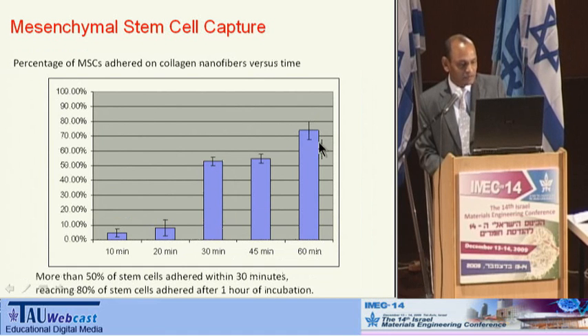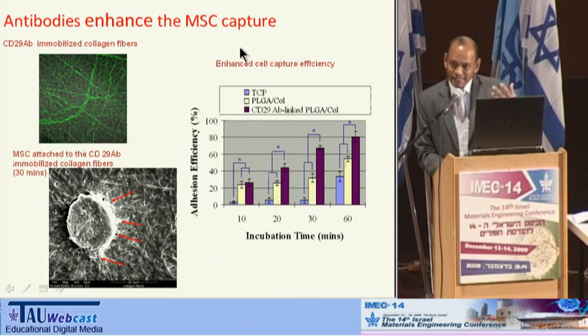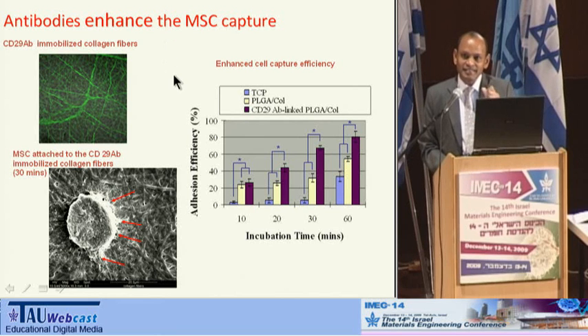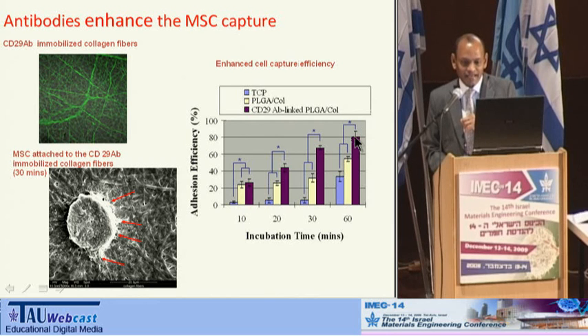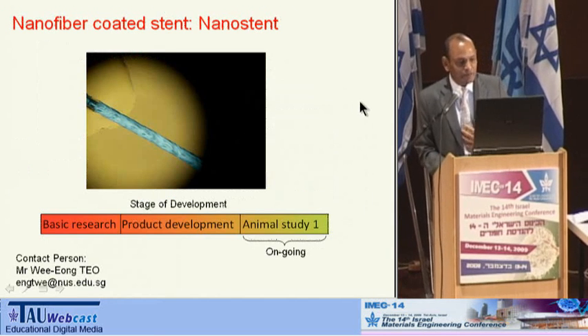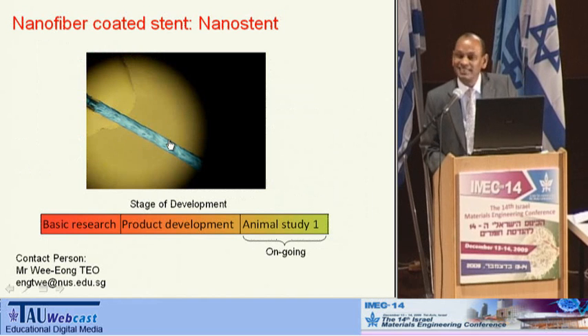And of course, if you further optimize it, you could get much higher levels of retention of the bone marrow cells, almost close to 80%. And then you can further enhance this by optimizing the surface of the collagen nanofibers with certain protein molecules, and you actually get to very high levels of retention of the stem cells. The whole idea is you have nanofiber scaffolds which are specially suited to absorb the mesenchymal stem cells from the bone marrow so that you can use that for treating patients in terms of the bone or other areas.